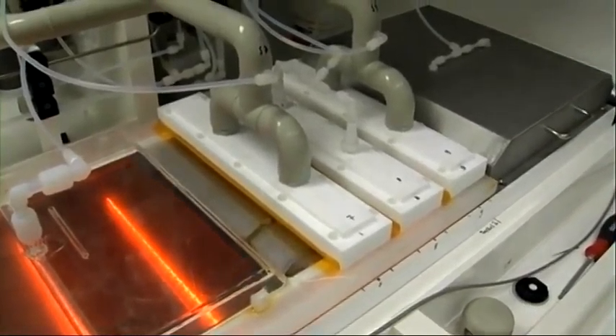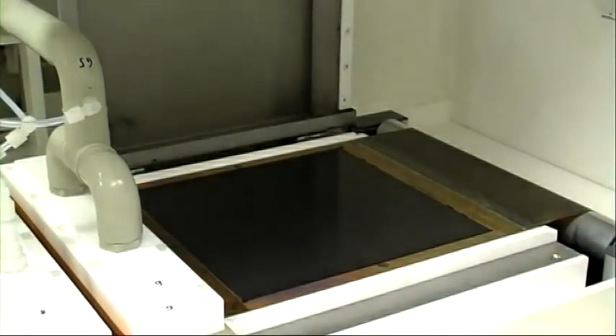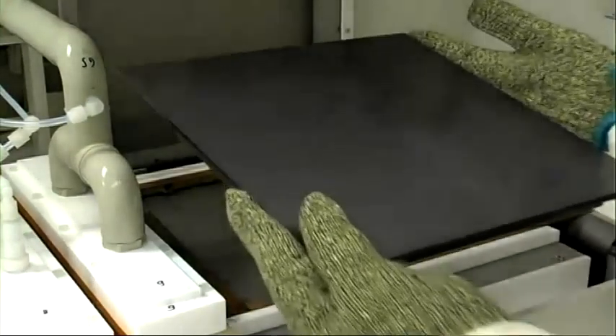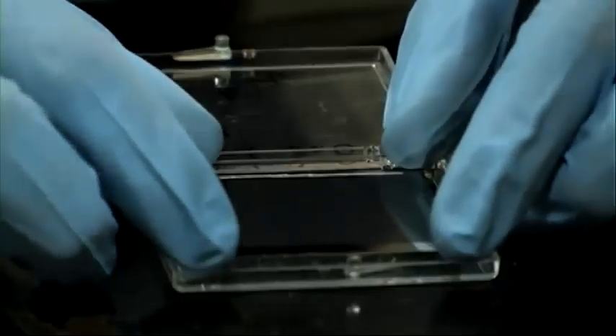This mist is then directed to the preheated substrate. Here the tiny droplets precipitate, gradually forming an even layer. Next, the layer is exposed to a reactive gas. This spraying and gas treatment process is repeated until the layer has reached the desired thickness.